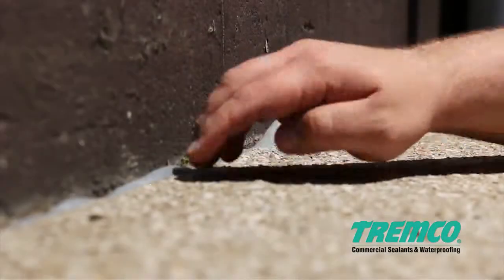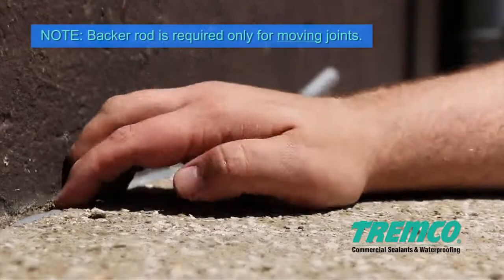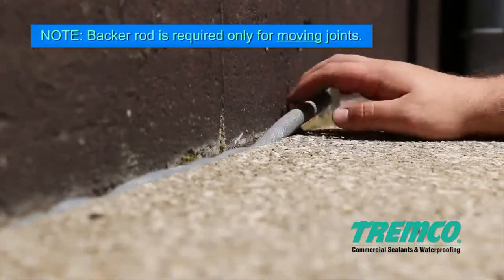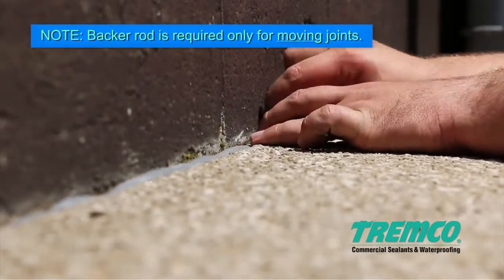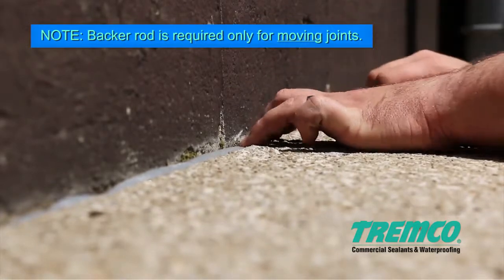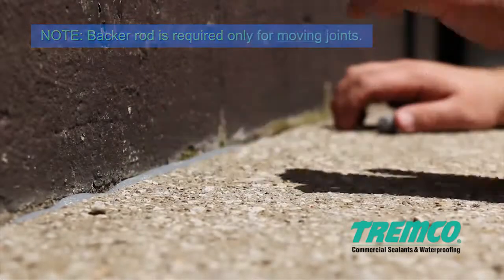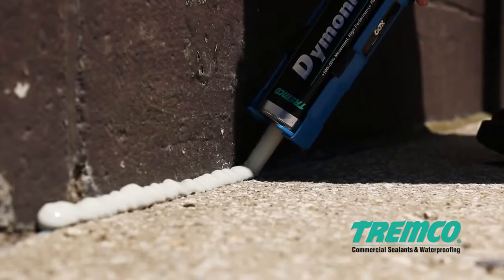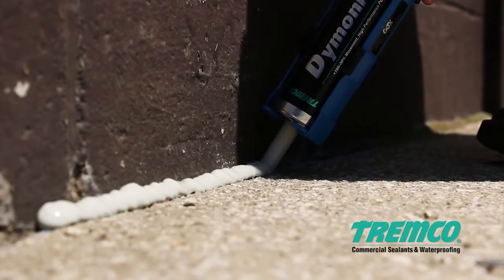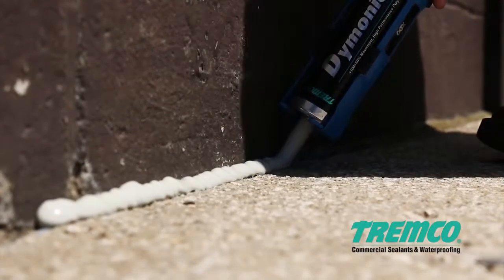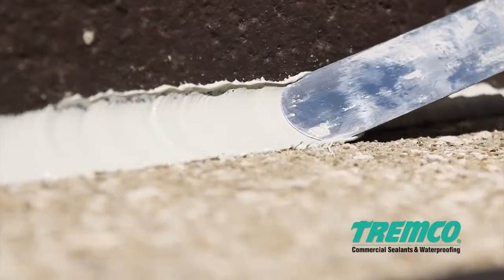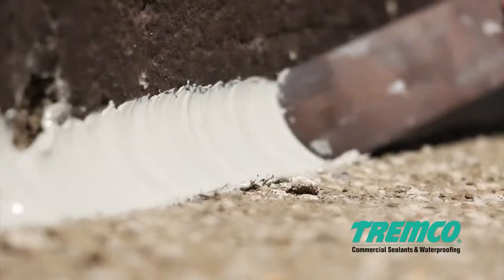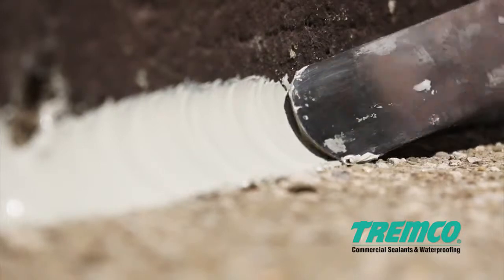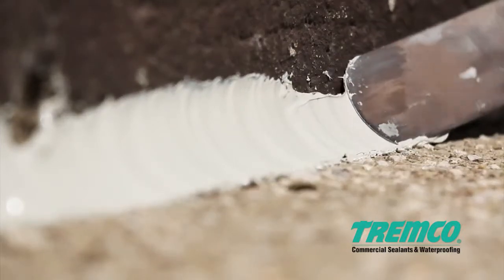For horizontal to vertical joints, lay the backer rod into the corner at the juncture of all horizontal and vertical surfaces, such as curbs, wall sections, columns, or penetrations through the deck. Then apply a bead of Dymonic 100 sealant 1 inch or 25 millimeters wide over the backer rod. Tool the sealant bead to form a 45-degree cant. Use sufficient pressure to force out any entrapped air and to ensure a complete wetting of the surface.